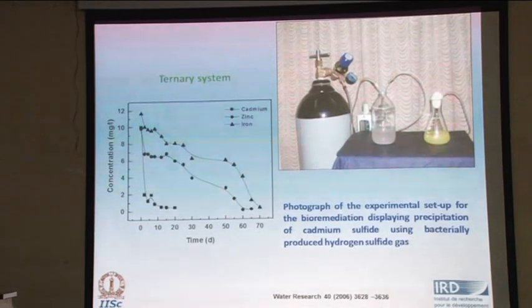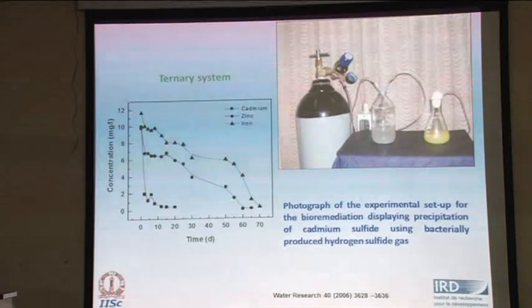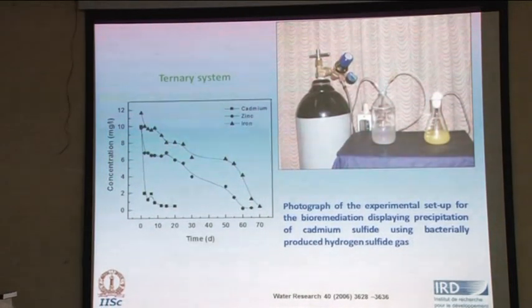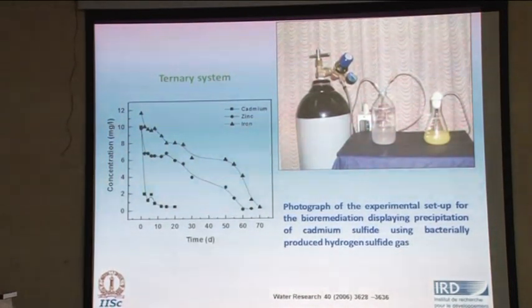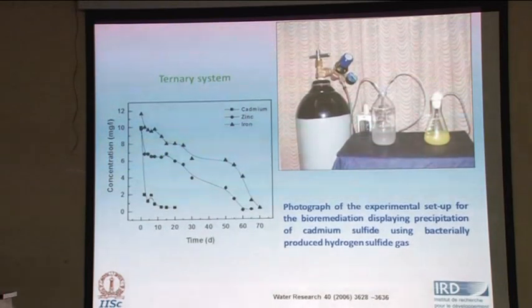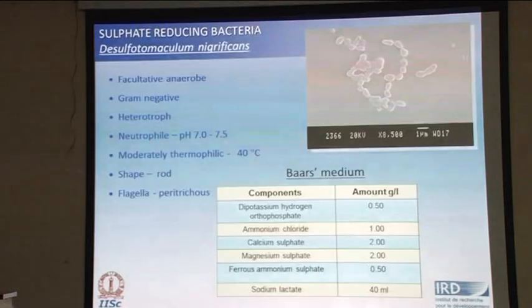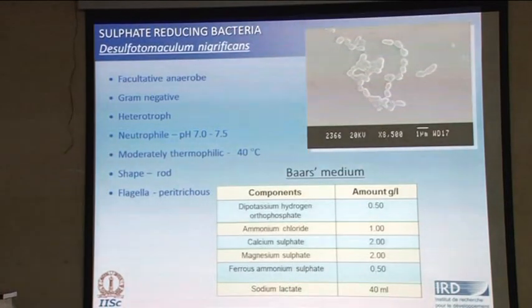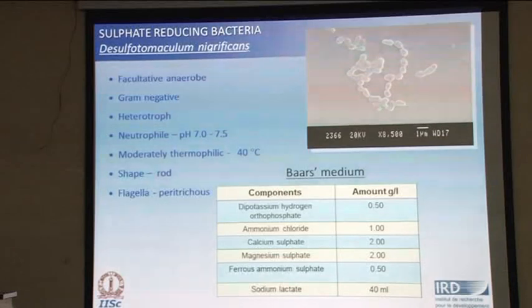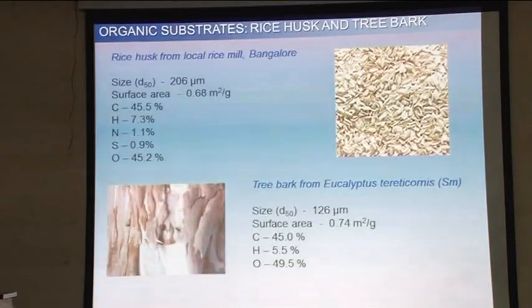And for those who are also interested in looking at nanomaterials, the precipitates which are produced here are all in the nano-sized range. And we have seen that they are different from the chemically produced sulfides. As we all know, for group 2, you add the Kipp's apparatus for producing the hydrogen sulfide, and we have done some characterization of these sulfides and found them to be different. Now, if you look at the sulfate reducing bacteria, I told you that in this case we have used the Desulfotomaculum nigrificans.